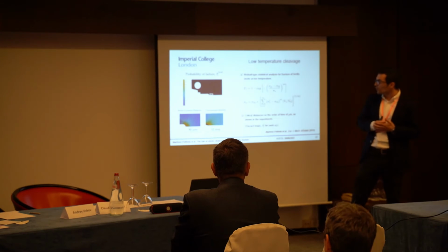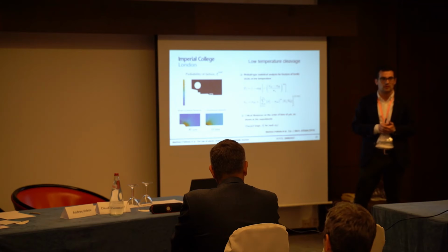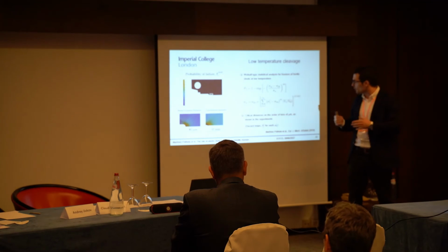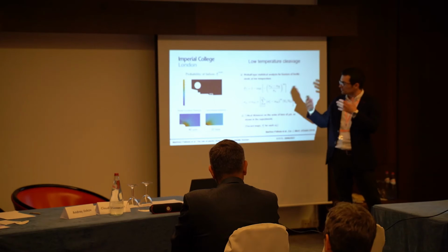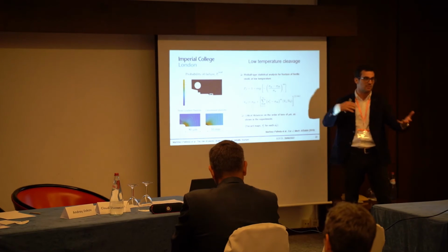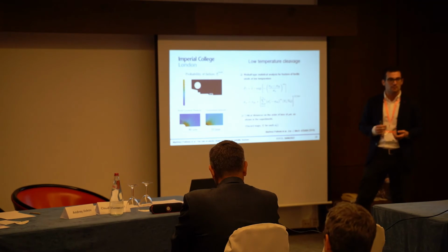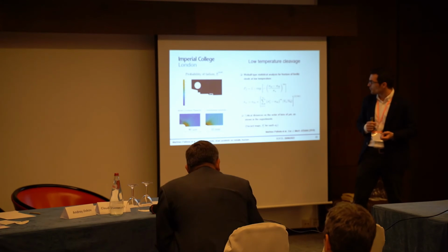Another case study is low temperature cleavage, so cleavage of ferritic steels at low temperature. And here we use a three-parameter Weibull model to fit the data with both conventional plasticity and gradient plasticity, and we got very different results in terms of the Weibull parameters.